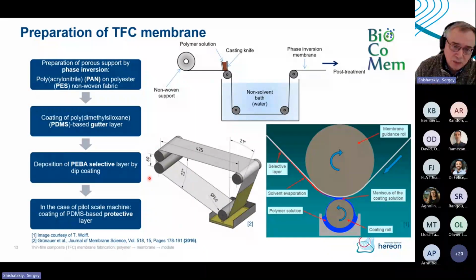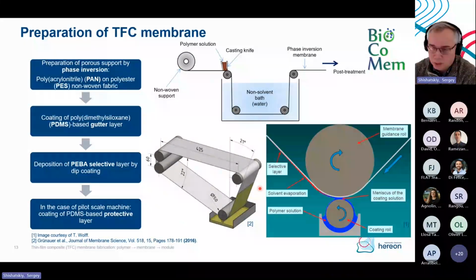For the small lab scale tests, we have a small machine, which is just about 1 meter by 60 centimeters high and 40 centimeters deep. And there, by a dip coating process, we are depositing the layer of a polymer. And here we start to understand whether this polymer can be deposited onto the support or it cannot be, and something should be changed. As soon as we start to get a membrane with properties which we consider sufficiently good, we transfer this process to the big machine, the pilot scale machine, which can produce membranes with 60 centimeter width and up to 250 meters long. And there we are using a modified dip coating method when we have two